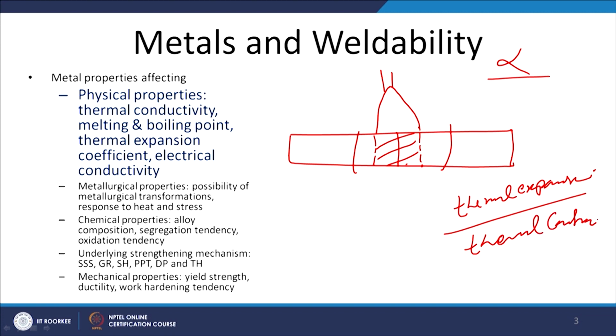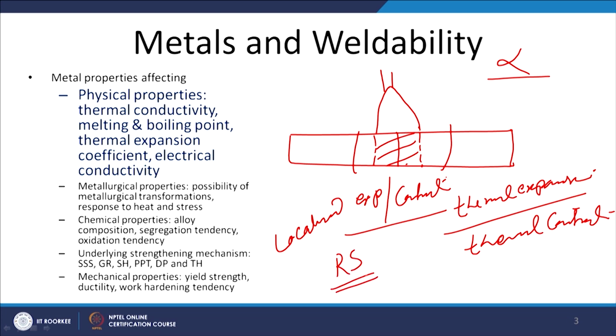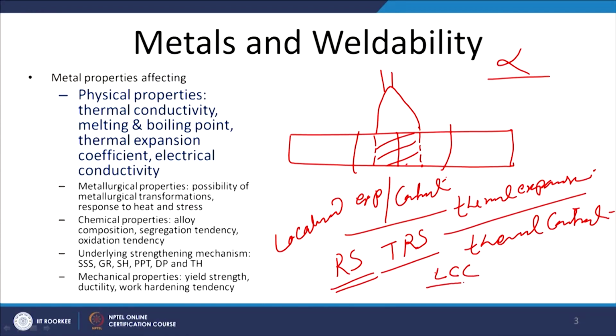thermal contraction. So, basically the problem is the localized expansion and contraction, which leads to the development of residual stresses, and in general, in the weld joint and the heat affected zone we get tensile residual stresses, which tend to distort the weld joint or the plates being welded. If the rigidity is limited, especially in case of thin sheets, the residual stresses lead to distortion, and especially the tensile residual stresses reduce the load carrying capacity and the fatigue resistance.